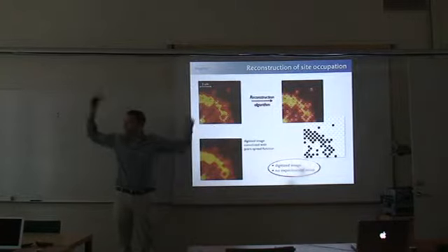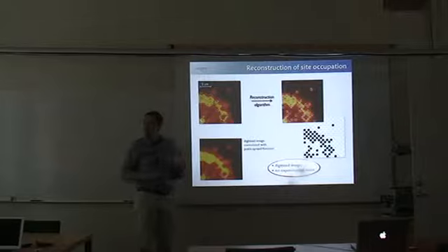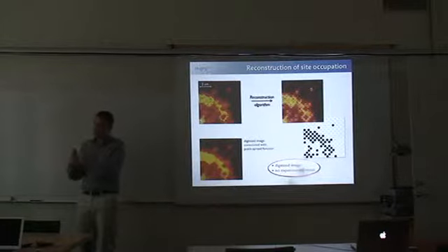Of course, we don't do this globally on the image, because that would be going through 2 to the 1,000 configurations. We don't have the computation power to do that. But if we go blockwise through the system, that's sufficient. We test around 250,000 configurations for each image to reconstruct this with this high fidelity. But to do that with high fidelity really requires knowledge of the particles on a lattice, so I know where fluorescence comes from, it's not a random position, and also that I have this projection method. I can know I only have 0 or 1 atom. That really tremendously helps, even if your spatial resolution is worse than the actual separation between the lattice sites. You can reconstruct the full image, the full distribution, modulo 2, with extremely high fidelity.